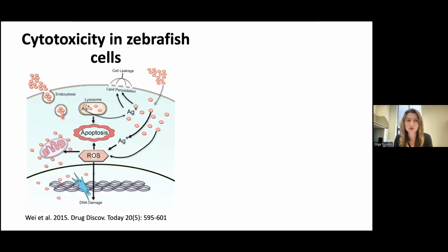However, if they go through endocytosis, eventually they will reach the lysosome. Lysosomes are a very acidic environment. The silver nanoparticles will be dissolved and silver ions will be released. As a result, there is an increase in the generation of reactive oxygen species. It can lead to apoptosis. It can affect mitochondrial performance. It can also cause some genotoxic effects.